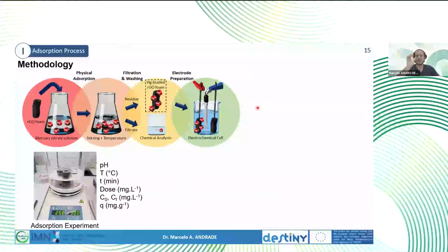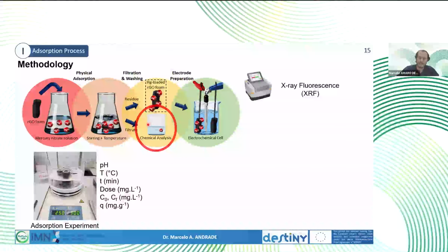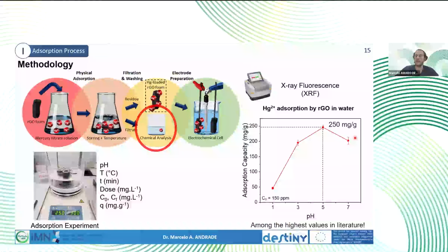The methodology process developed was very straightforward. Basically, the RGO synthesized foam was mixed in the model wastewater solution, which was a mercury nitrate solution with known concentration, with distilled water, no other competing cations, stirred for a certain time, and then the foam was recovered to make the electrochemical cell. We wanted it to be as straightforward as possible with low energy input, right? And then we would analyze the water to see how much of the mercury was adsorbed by the RGO foam. And we reached 250 milligrams of mercury per gram of foam at pH 5, which is among the highest values in literature. So RGO demonstrated to be a very efficient adsorbent.